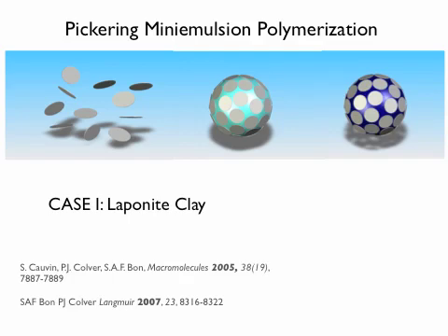so it's quite a while back. We developed the idea that if particles stick at liquid-liquid interfaces, you can almost say the molecular equivalent would be a surfactant molecule adhering to a liquid-liquid interface, so maybe particles can act the same as surfactant molecules. And so you could imagine if I have a mixture of oil and water, with particles present, and I shake, these particles go around the droplet, and maybe I can influence the size of the droplets if I vary the amount of these particles.